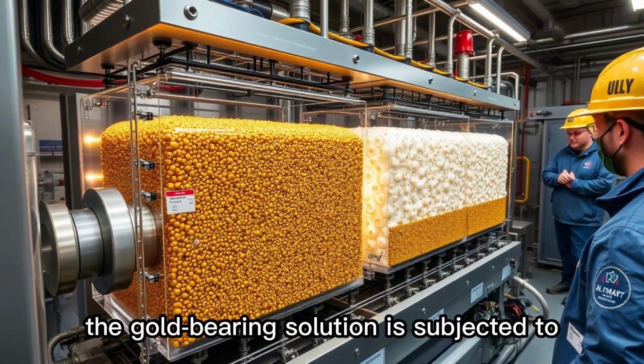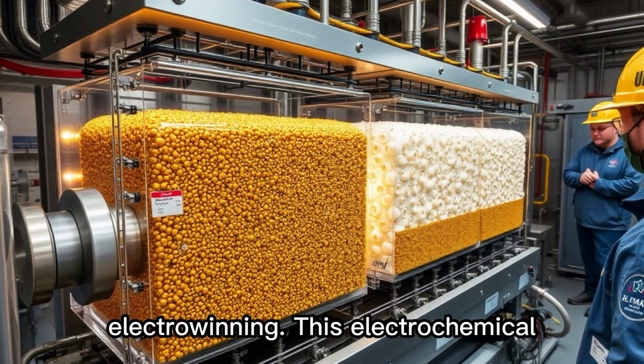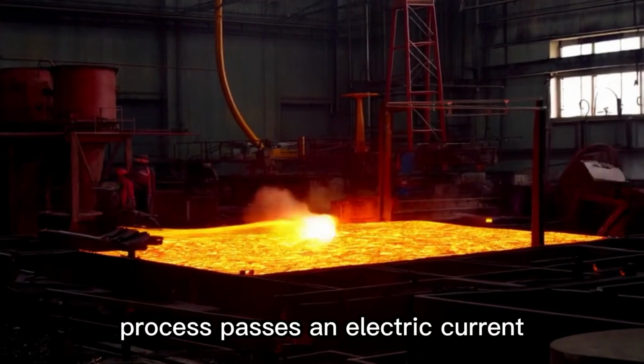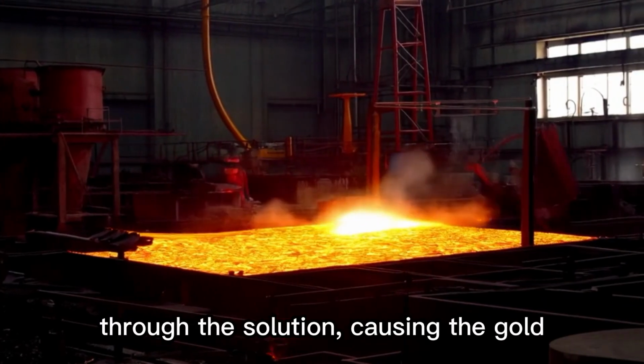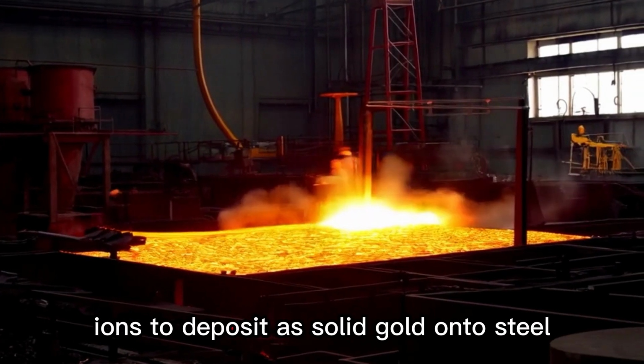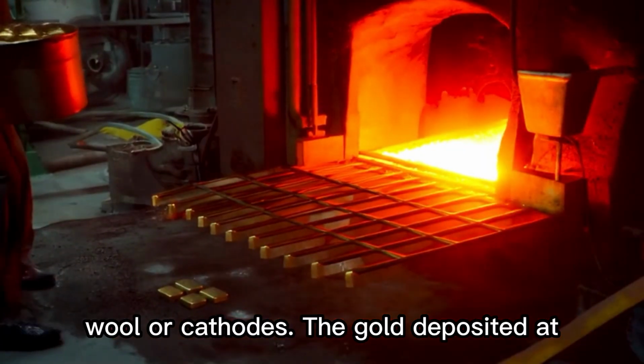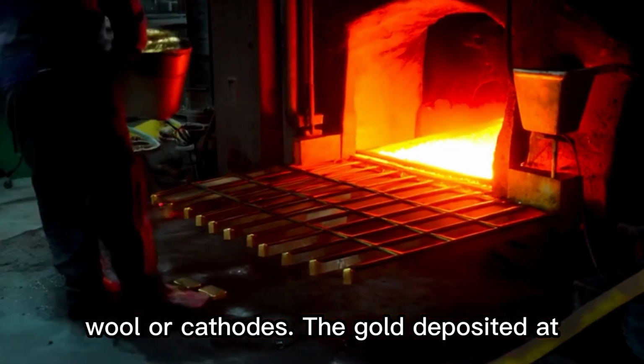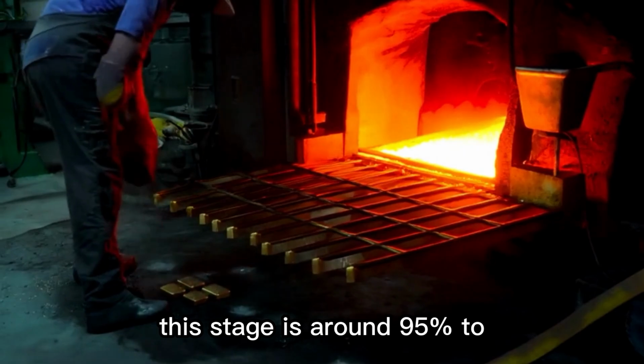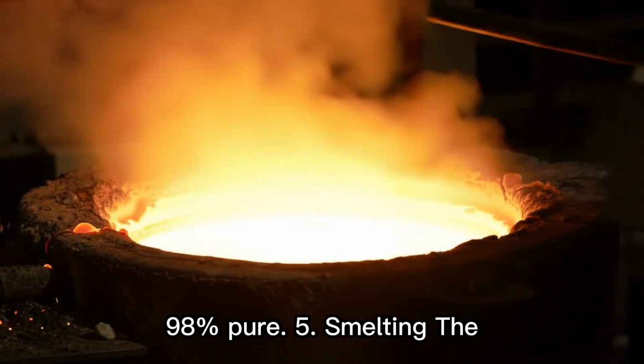4. Electrowinning. In this stage, the gold-bearing solution is subjected to electrowinning. This electrochemical process passes an electric current through the solution, causing the gold ions to deposit as solid gold onto steel wool or cathodes. The gold deposited at this stage is around 95% to 98% pure.